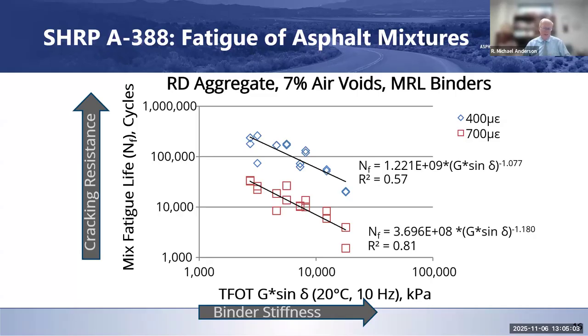If you choose a test like the Texas overlay test, it's a really high strain test. So you might rank order your materials a little differently than if you chose a test like the flexural beam fatigue test and you ran it at a low strain, like 400 microstrain. You might get a different rank order because it's different sorts of cracking mechanisms that perhaps you're looking at. So I think that's where some of the challenge is whenever we talk about just choosing a cracking test within a balanced mix design environment. You kind of have to know what cracking you're focused on, what's the most important, and how is that test going to pick up on the relevant parameters that you think are going to be important to both fatigue cracking and perhaps durability cracking.